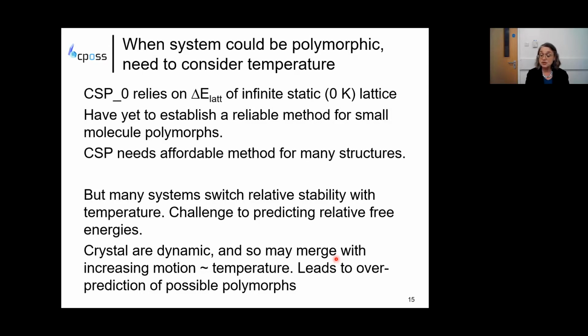Their pharmaceutical tablets have to remain stable with the right polymorph because its dissolution rate is very dependent on the polymorph, and that's why you're only licensed to market your drugs as one known polymorphic form. But you can't get your polymorph in your product changing to another form as it's stored. And if you think of the range of temperatures, humidities and pressures you get around the world, you can see that that's quite a challenge. So we want to be able to predict the relative free energies of the known polymorphs.